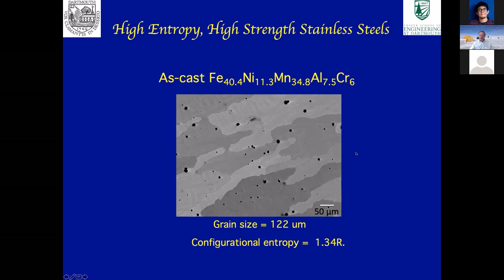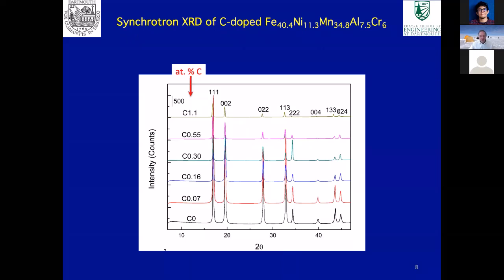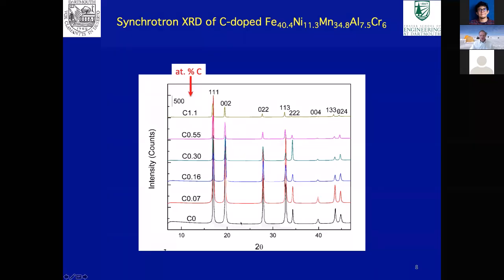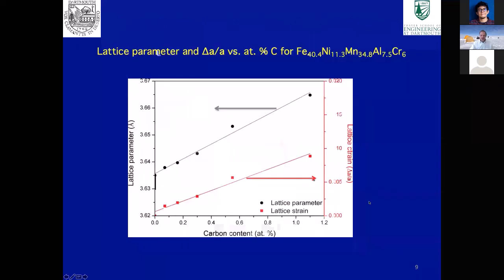So this is a typical microstructure of this material with a grain size of over 100 microns. And we've actually looked at these with different amounts of carbon. This is X-ray diffraction data from the Argonne synchrotron. The 0 means no carbon, 1.1 means we've got 1.1 atomic percent carbon. You can see for all of these we've got the same diffraction peaks, and they're all face-centered cubic. If you look at the lattice parameter as a function of carbon content, it's pretty linear, and so is the lattice strain, indicating that the carbon is really in solution.